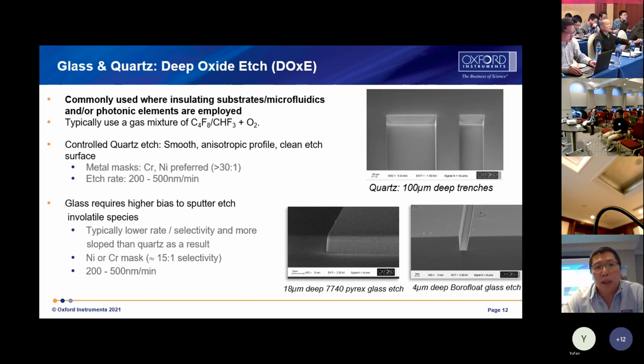Glass is commonly used as an insulating substrate or photonic element. Typically, we use fluorine-based plasma to etch quartz or glass. The etching rate is 200 to 500 nanometers per minute, depending on the aspect ratio size. The higher the aspect ratio, the slower the etching, with good uniformity with a metal mask. Glass with impurities contains involatile species, so you need high ion bombardment to remove them and keep a smooth base. The etching rate selectivity is slightly lower than for quartz material. You can see the ICP etch shows a slightly sloped profile.